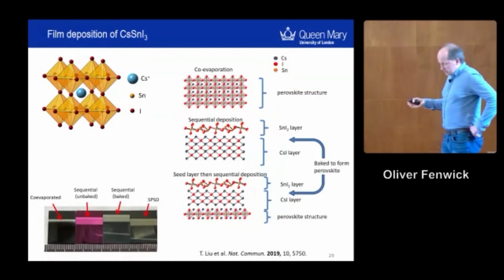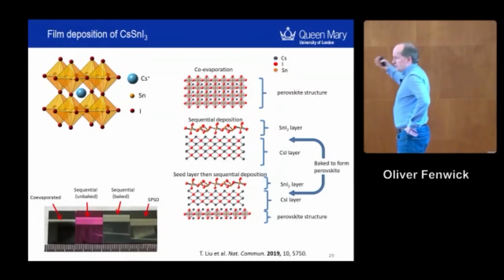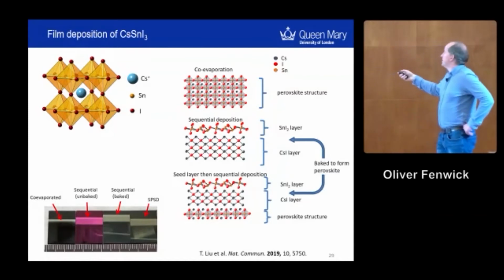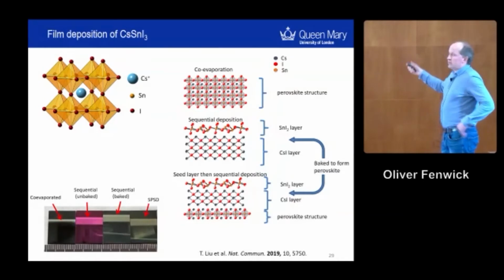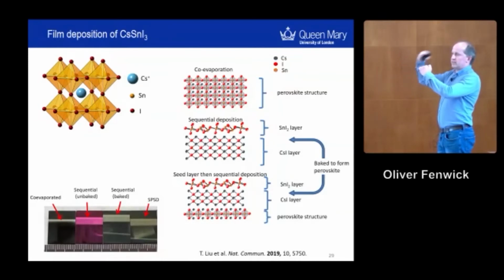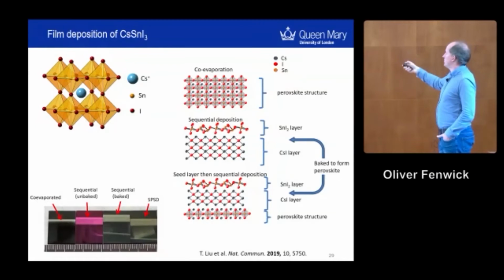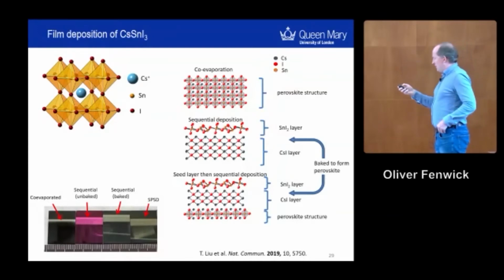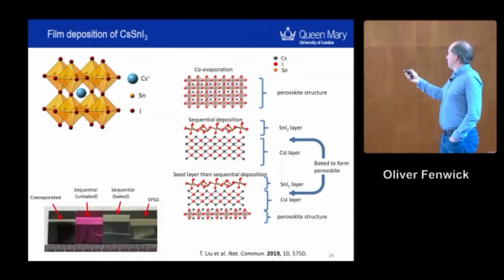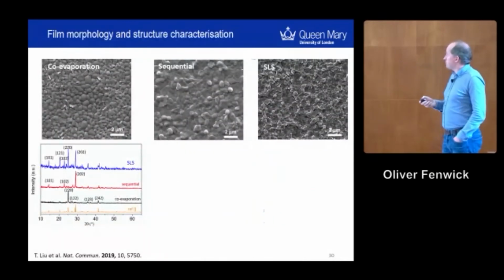And again, we deposit by vapor deposition from the precursors cesium iodide and tin iodide and use 3 different techniques. So one, we co-evaporate the precursors, they react on the surface together. Another, we put one layer down first and then the other sequentially, and then bake them afterwards to make the perovskite. And then we do this hybrid method where we do a co-evaporated seed layer plus a bit of sequential deposition afterwards to get a kind of mixture of the 2. And that turned out to be particularly useful.